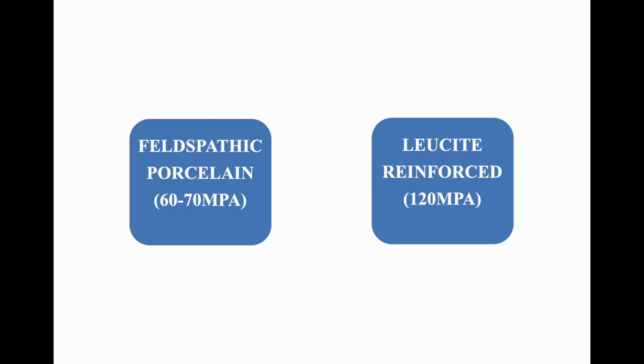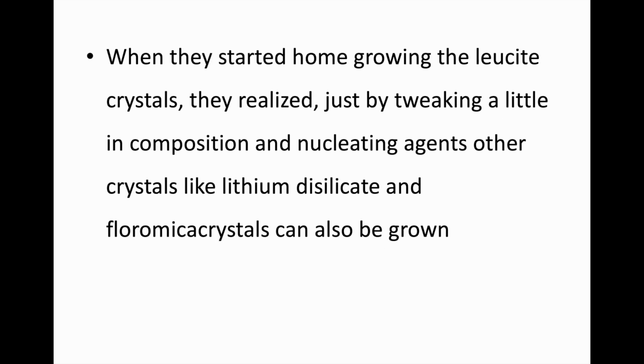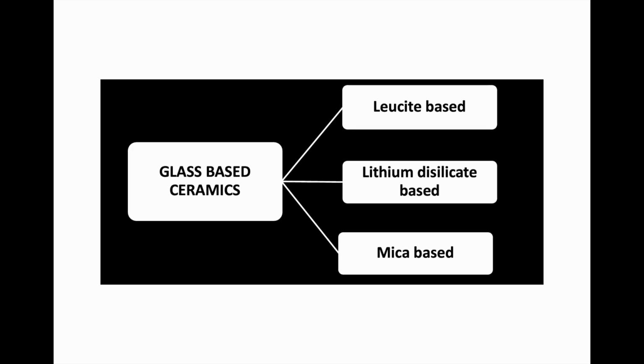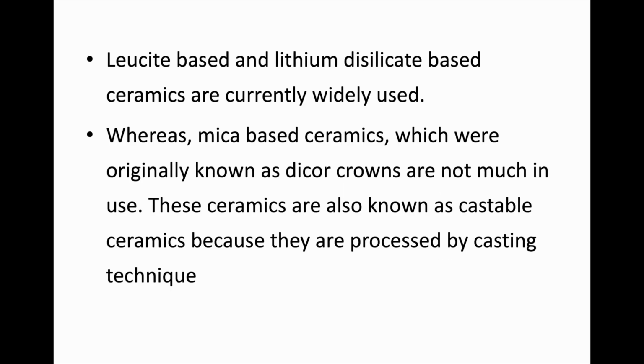Feldspathic porcelain showed flexural strength of 60 to 70 MPa, while leucite glazed glass ceramic showed a flexural strength of 120 MPa. This was almost doubled up. When they successfully started home growing the leucite crystals, they realized just by tweaking a little in composition and nucleating agents, other crystals like lithium disilicate and fluoromica crystals can also be grown in the glassy matrix. Like this, a total of 3 groups of ceramics were added in this category. These ceramics are called as glass-based ceramics, and the 3 categories under this group are leucite-based, lithium disilicate-based, and mica-based glass-based ceramics. Lucite-based and lithium disilicate-based ceramics are currently widely used, whereas mica-based ceramics, which were originally known as Dicor crowns, are not much in use.